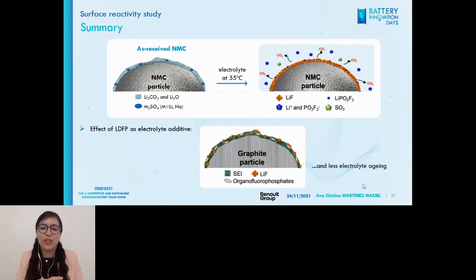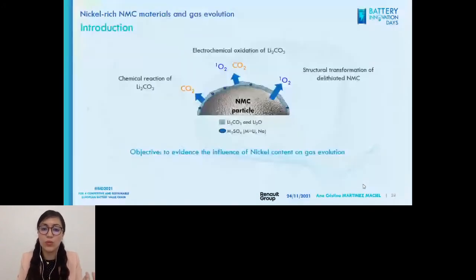Now that we have been seeing gas appearing everywhere, this is the time to relate the surface reactivity with gas evolution. As an introduction, we know that NMC materials produce gas, even if normally it's not acknowledged. There are surface reactions such as chemical and electrochemical oxidation of carbonates that produce CO2, active oxygen as well. And there is also this structural transformation of the delithiated NMC that produces active oxygen.